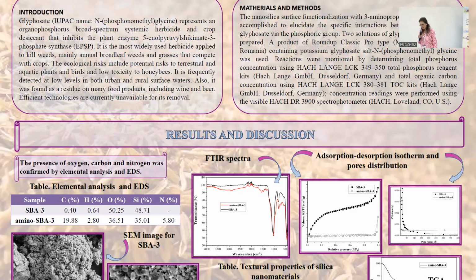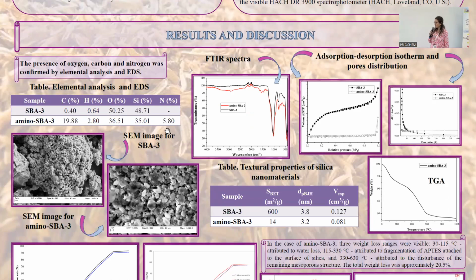As you can see, in the amino material, we have a concentration of around 6% of nitrogen, confirming that the functionalization was achieved. Also, the FTIR spectra confirmed the appearance of aminopropyl vibration, and the specific surface decreased radically from around 600 for the raw material SBA-3 to 14 square meters per gram in the amino functionalized material. The SEM morphology showed spherical and spheroidal particles for the materials.